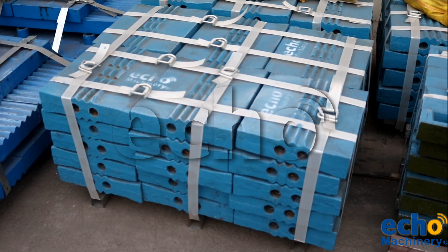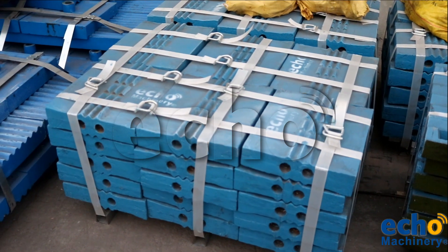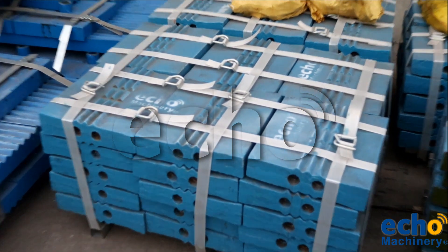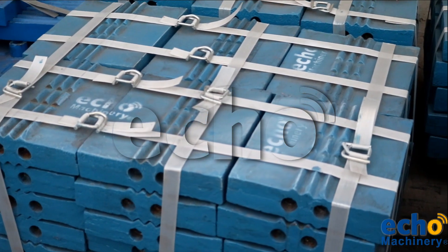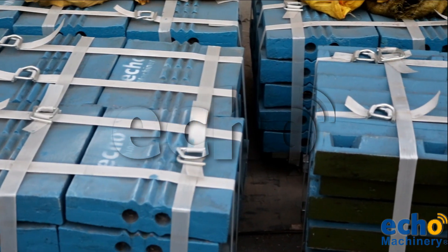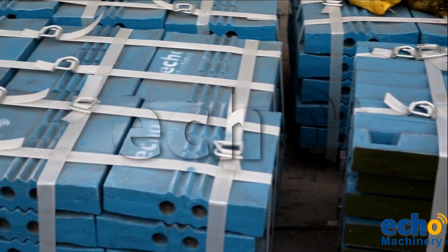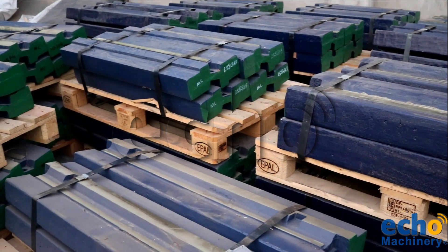The third one is chrome steel. Typically, the hardness ranges from 60 to 64 HRC. To prevent the material from becoming brittle, we have special heat treatment. Thus, it has high wear resistance. Its size needs to be controlled due to the risk of breakages, and it won't tolerate steel in feed.